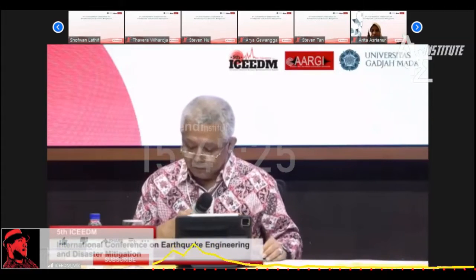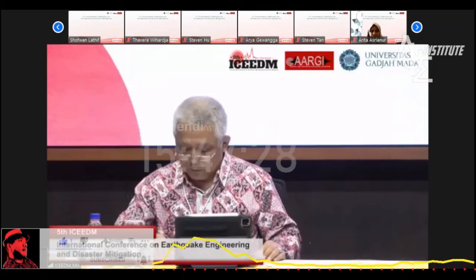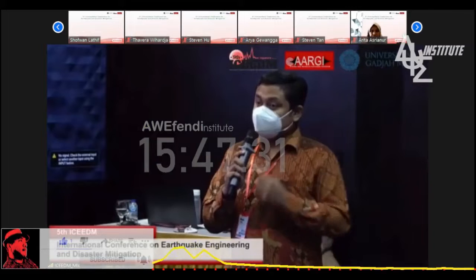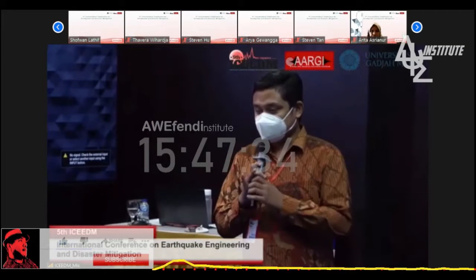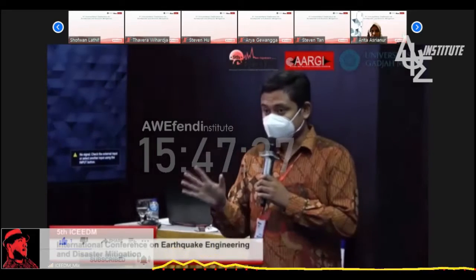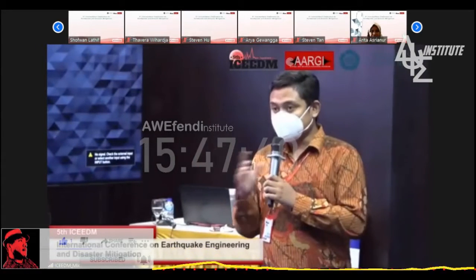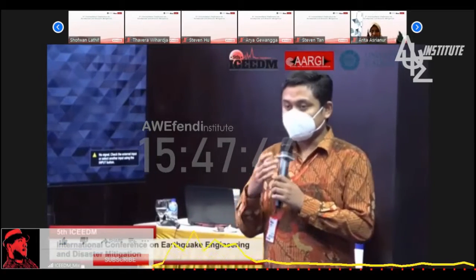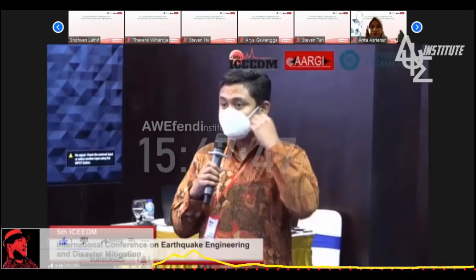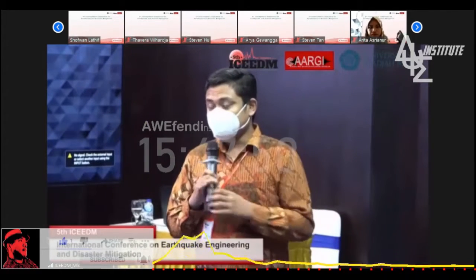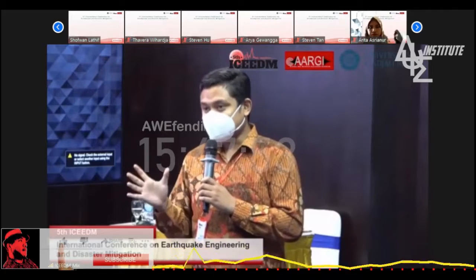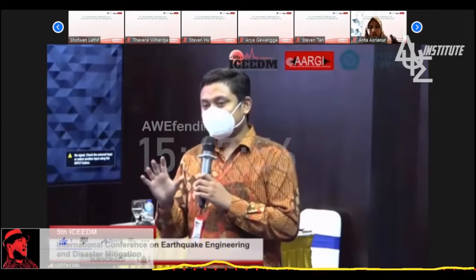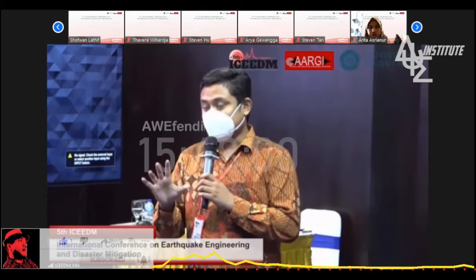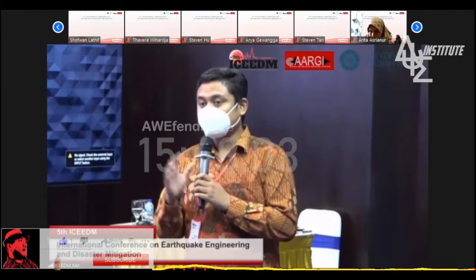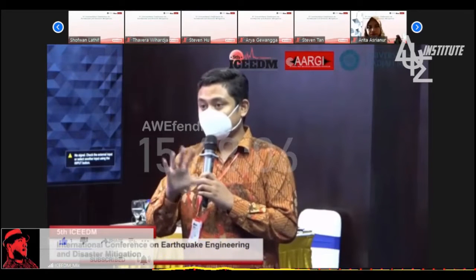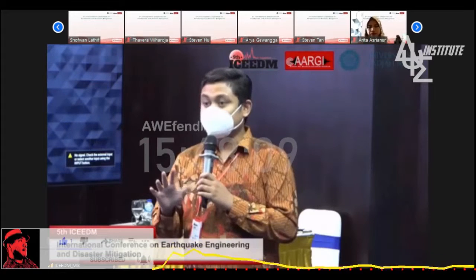Thank you for the excellent questions. I'm going to answer the first one. When we did the test, basically we have 4 specimens, only 2 specimens for direct comparison between normal concrete and ECC specimens. At the end of the test, we see different crack patterns in concrete and in ECC. In the concrete specimen, the crack mainly occurs at the interface in the beam column joint and also extended towards the joint core. So we have some diagonal cracks in the joint core.